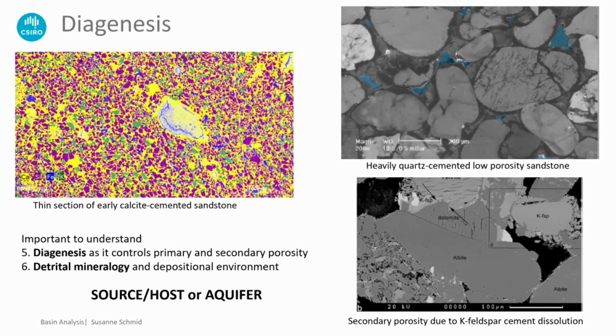So on the left, you see a thin section scale of arkosic sandstone, immature sandstone, and the yellow bits, that's calcite cement. So it's been cemented up. If you calculate the yellow bits, it's probably like 30-40% of the sample, and you see the grains floating in that calcite matrix. That usually means it's been calcite cemented very early in the basin formation due to evaporation. So that's early diagenetic. It happens pretty much straight after deposition, blocks all the porosity, and it's sealed.